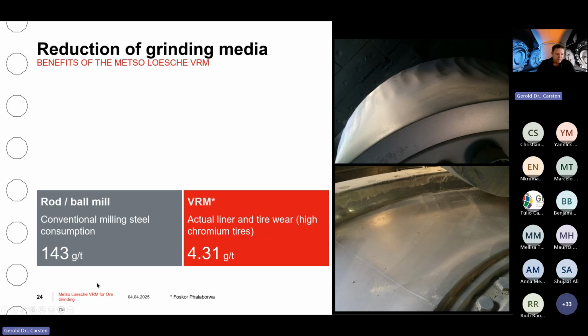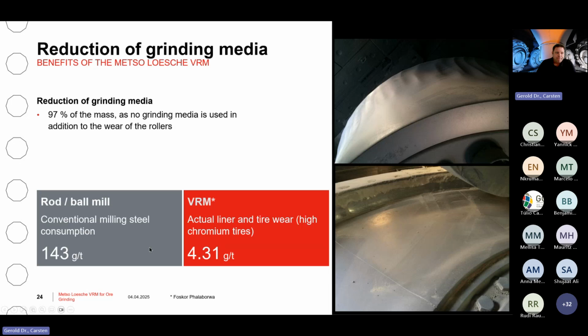But in this case, it's a phosphate rock. It has a Bond work index of 24 kilowatt hours per ton. The comparison of wear is that 143 gram specific grinding media consumption is achieved with a rod and ball mill, and the VRM has about 4.31 gram per ton, so massively lower. That's about a 97% reduction. And that surely is very positive for flotation because you have less metal in flotation, but you also have a 40% cost saving. And if you consider the production of the metal, it's also significant CO2 savings.